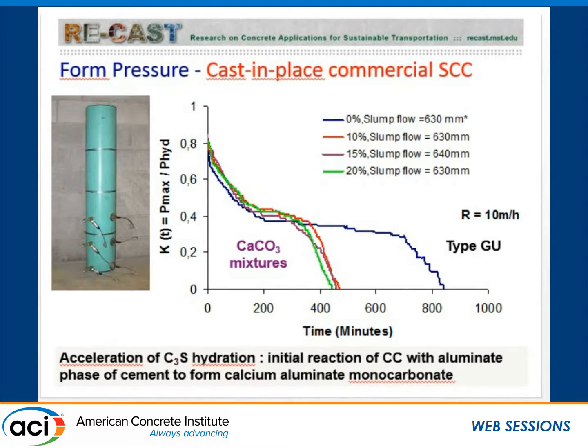And we see whether you are using a type 1 cement or calcium carbonate, initially nothing changes. It's the same rate of decay of pressure. But with the calcium carbonate, we get a much faster decay in pressure. And that's very important. So that's the first indication that tells us that this limestone that is very fine is doing something to the hydration of the cement in the dormant period.